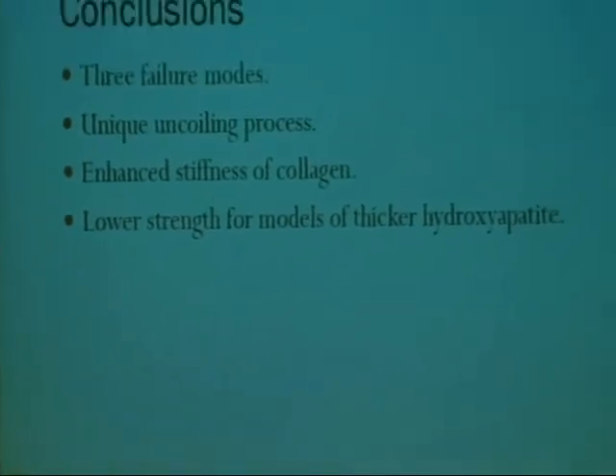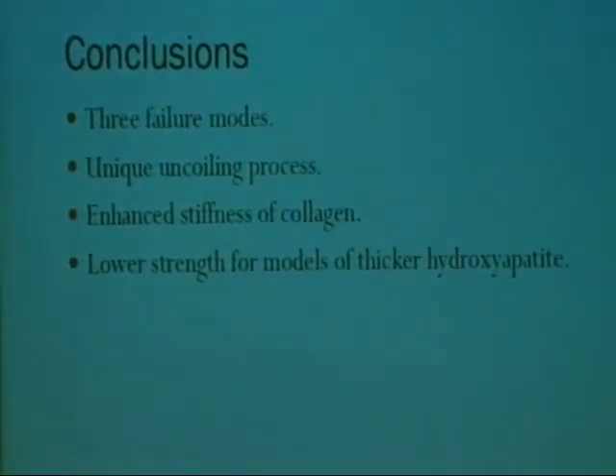The significance of this research is that we have proven for the first time the enhanced stiffness of collagen at the molecular level. Previous research mainly studied the enhanced stiffness of collagen fibrils and the overall enhancement of bone with the mineral phase, but not the actual increasing stiffness of the collagen molecule itself. For further study, we might apply this to different surfaces of the hydroxyapatite — in this study we examined only the calcium surface. Another option would be studying the system in water, since this was a dry system.